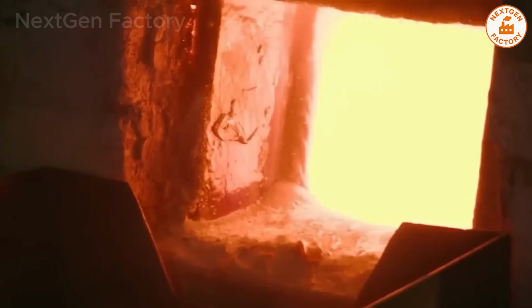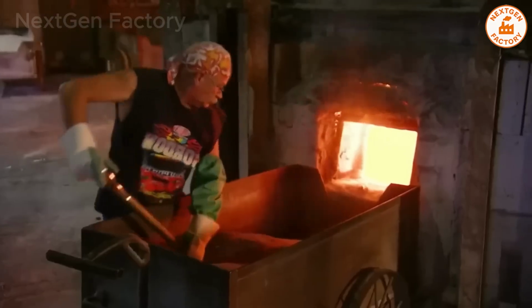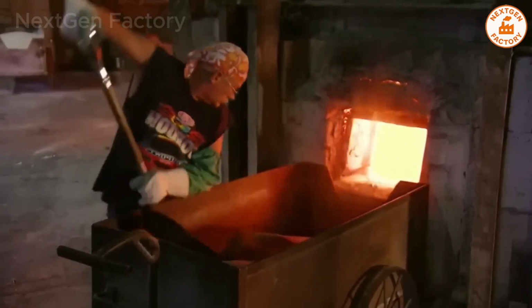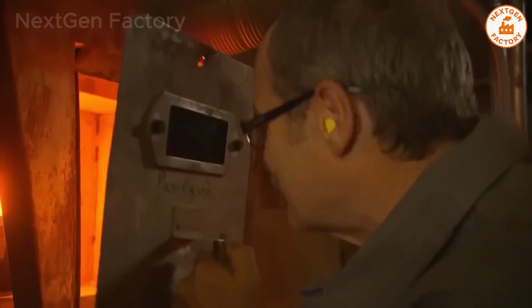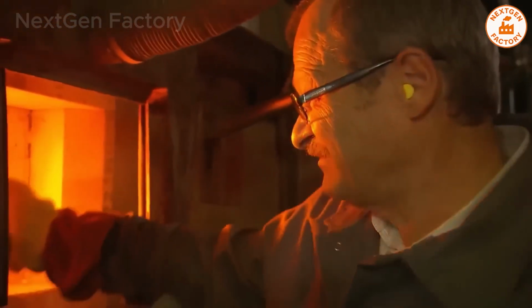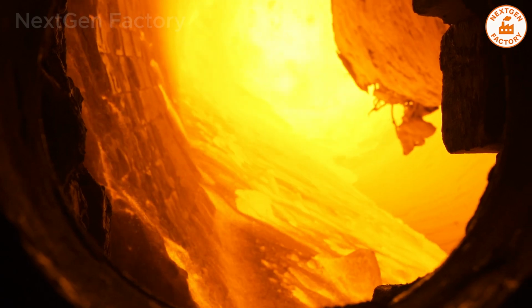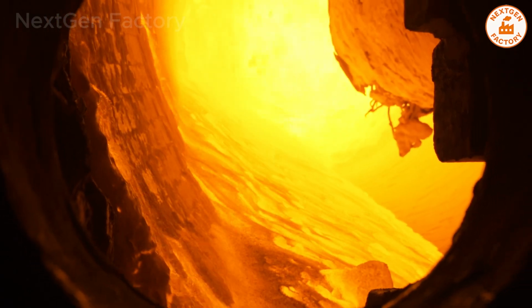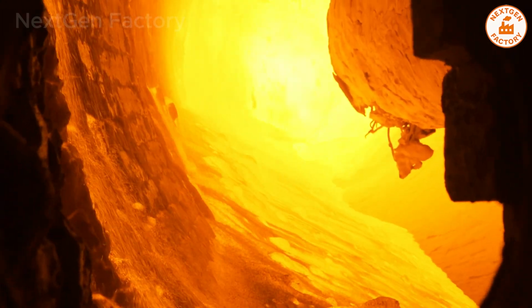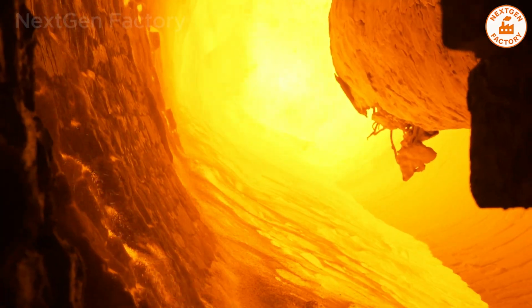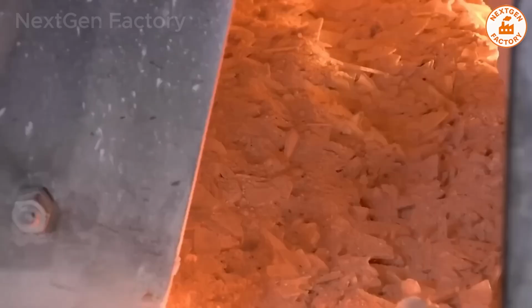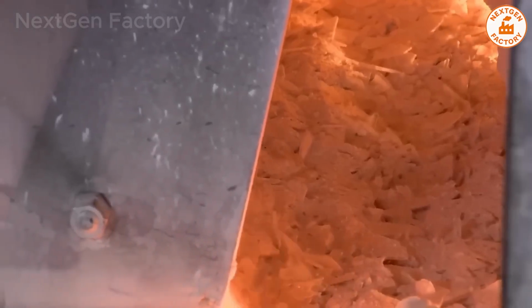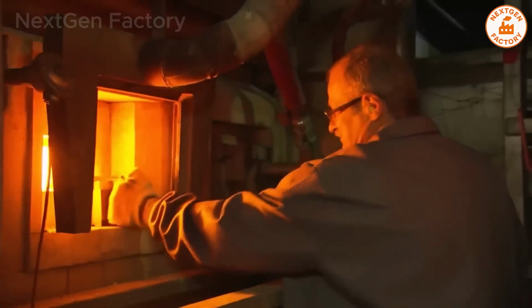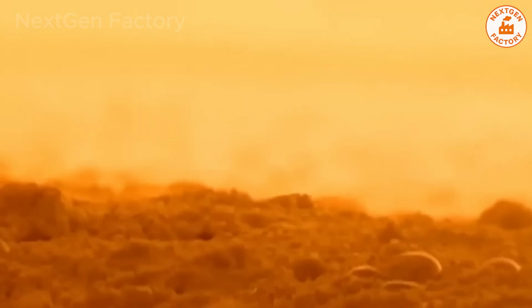The mixed batch is fed into the heart of the factory, the melting furnace. These furnaces are engineering marvels, giant chambers lined with refractory materials designed to withstand temperatures above 1,600 degrees Celsius. Inside, the batch slowly melts over 24 hours. Sand grains soften, collapse, and merge into a glowing, honey-like liquid. Impurities rise and are skimmed off. Bubbles escape during a stage called fining.